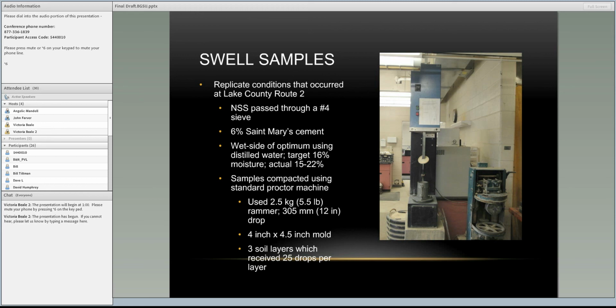So we had 6 wet, 6 dry. Of the 6 wet, 3 were placed in distilled water, and 3 were placed in a 7,000 parts per million sodium sulfate solution, and likewise the same was done with the dry samples.